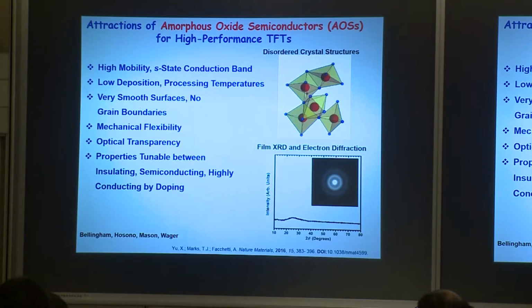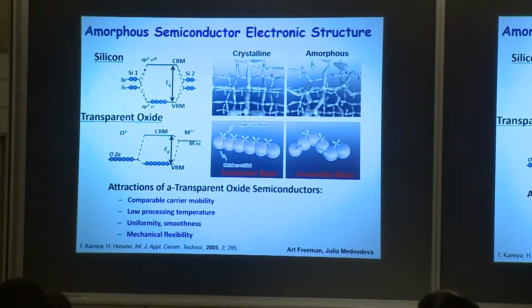A lot of them are quite flexible, as we'll see. Some very smooth surfaces. So in terms of electronics, if you want to contact different layers, you want smooth surfaces. These have all of those properties. Tunable optical transparency, they're essentially a glass, a semiconducting glass. And don't think of it as a random mixture of oxides and metals. In fact, we've done XAFS and a lot of things, and the metals still have very definite preferred coordination numbers.